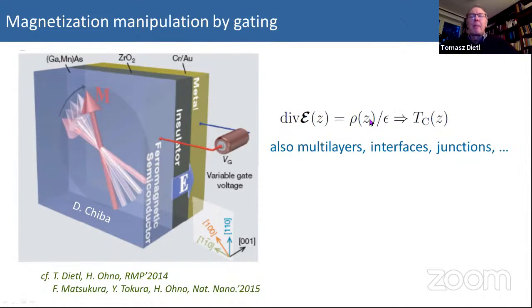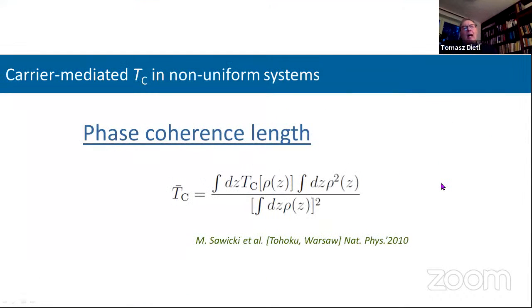So the question arises of how to describe whether the maximum of TC or the minimum of TC determines TC in such an inhomogeneous system. And I think a new interesting concept here is to realize that what counts is the phase coherence length. Actually, the phase coherence length determines the length scale over which TC should be averaged to obtain the TC which is observed experimentally. Such a theory was developed some time ago, and the formula for this averaging of TC, giving the macroscopic TC in a system which is homogeneous on dimensions smaller than the phase coherence length, is given here.